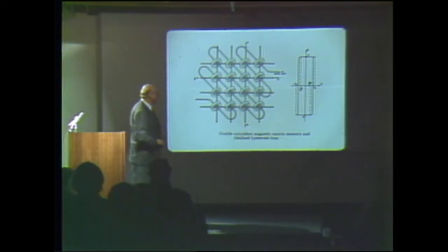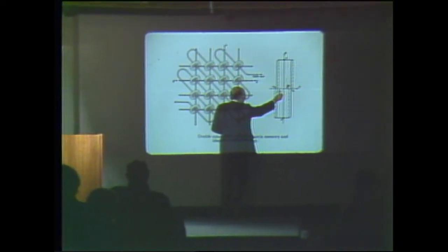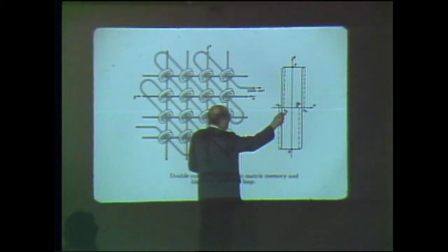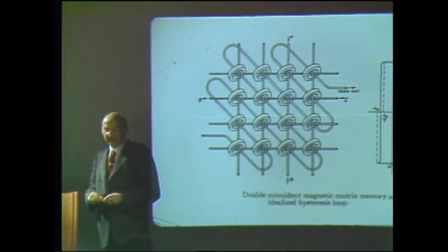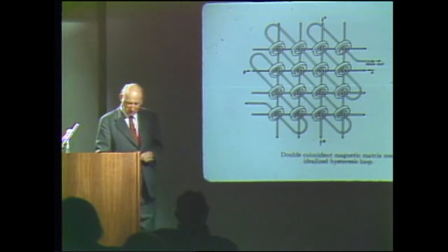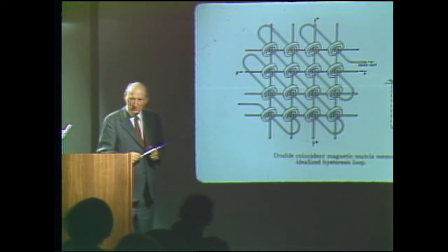And so I asked some of the people who had developed ferrites, who didn't want any hysteresis loop at all. They wanted a straight line, because as is well known, the hysteresis loop produces heat losses. And of course they didn't want that. And so all their skills were used to make no loop at all. So I asked them, well, could you make a square loop? And to my great amazement, in 6 months, they synthesized a material that had a square loop. And it turned out there were, in fact, many materials that had them.